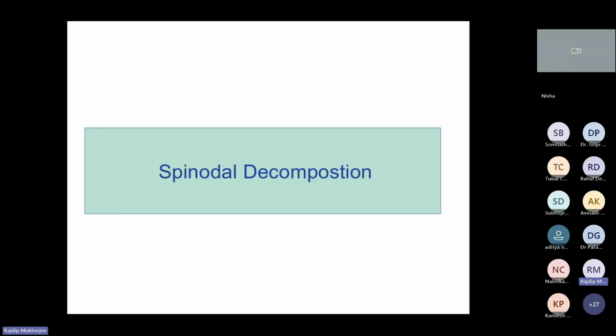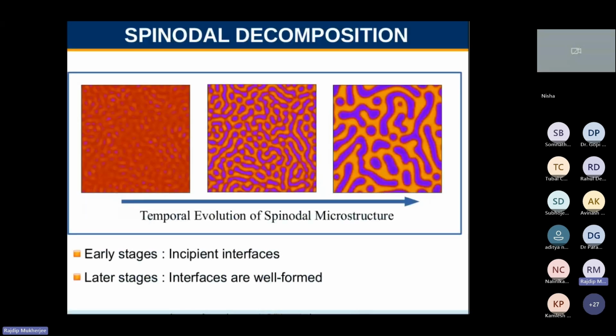This is also a kind of phase separation where an alloy decomposes into two or more phases, right? So you can see this is a temporal evolution of a spinodal microstructure. You start with a homogeneous system where the composition is homogeneous everywhere, and it then decomposes into two phases, this orange and purple color, right? These phases will coarsen with time. So the arrangement and volume fraction of these phases are important to understand the property of that particular alloy.